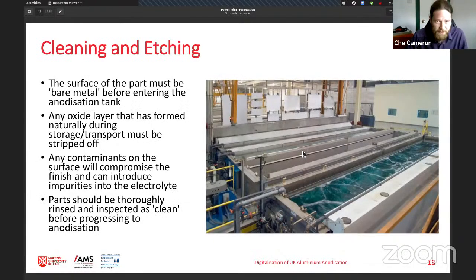Once you have your parts loaded into jigs, again, we're going to clean again, because as I said, this is a clean line and there's a lot of cleaning processes. Usually several different series of rinses and cleans are done to the parts before they even start anodization. So assuming you manage to get all the machining oils and any other contaminants off, you will still have a natural oxide layer, which is just formed by the aluminium being exposed to air. Now, this isn't the oxide layer we want for anodization, so that has to be etched off before the anodization process begins. And it's essential that parts are completely clean and completely bare metal before they enter the anodization tanks.